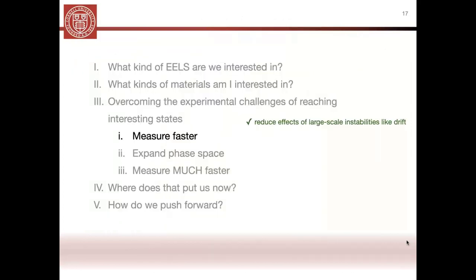And so really, the trick so far is just we want to outrun this drift. And so the first thing you do is, if you're trying to outrun something, you go faster, right? And so by measuring faster, we've been able to reduce the effects of these sort of large scale instabilities such as drift. We can demonstrate this two-dimensional mapping, really this is enabled by the fast and low noise detector hardware that we had installed on that particular instrument. So that's a great jump forward for us.